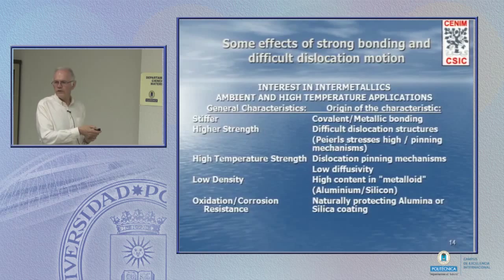So summarizing, and it comes from the strong bonding and the difficulty of dislocation nucleation and motion, we're elastically stiffer. We've got higher strength, for two reasons: it's a difficult dislocation structure and the Peierls stress. High temperature strength, if we can pin dislocations, low diffusivity.